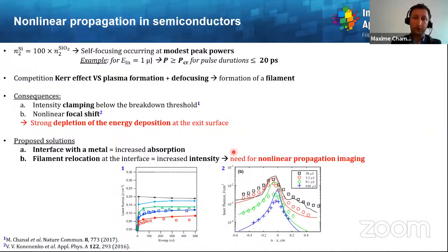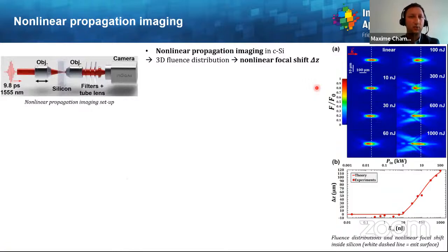But to do so, we need nonlinear propagation imaging, and this is actually exactly what we did. We imaged the nonlinear propagation inside silicon by means of this setup, which is nothing else than an inverted microscope. And it allows us to evaluate experimentally the 3D fluence distribution inside silicon for different input pulse energies indicated here, and thus the nonlinear focal shift delta Z as shown here as a function of the input energy.